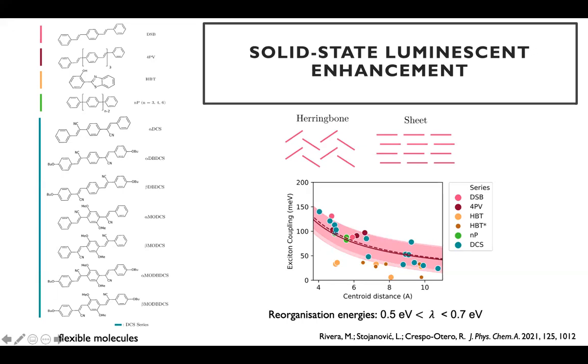And you will see that for this set of systems that we have here, and as I mentioned before, we have a lot of rotatable bonds here, we can have systems that can really access conical intersections. You will see that for most of the systems, and for all of the systems, the reorganization energies will be significantly larger than the values of the exciton couplings. And because of that, we can talk about very localized excited state processes in these systems.